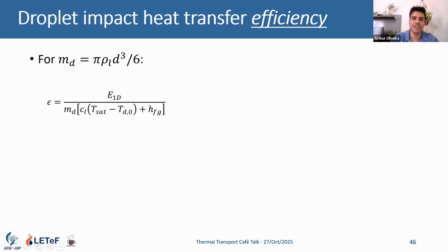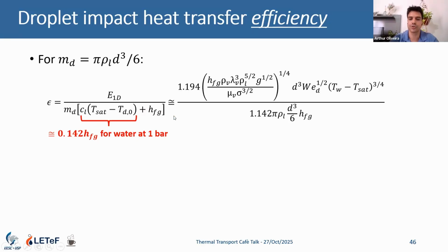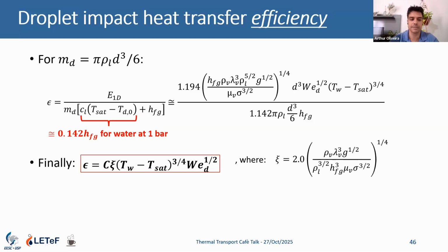And then when we put that together, we have this equation for the amount of energy which is dissipated. So if we put that as an efficiency, it suffices to divide that by the maximum energy it could dissipate. And if we take that for water at 1 bar, the sensible heat is about 14% of the latent heat. So if we take this and put it all together, this big equation becomes a very simple correlation.